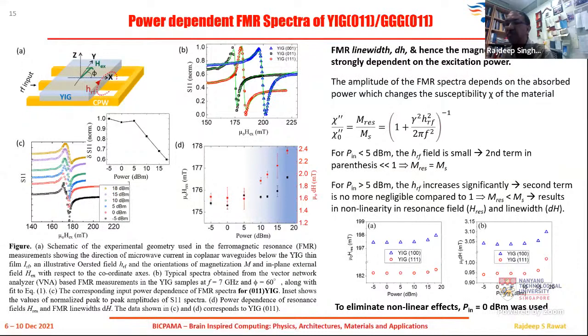But first of all, we wanted to make sure this two-magnon scattering does not come from the use of very high power. So we wanted to see the region where the response can be nonlinear by itself just because of the power, and we did not want to work in that region. So the input power was changed, because even a high input power can cause line width broadening as well as magnon excitation. The power was changed from -5 dBm all the way to about 18 dBm, and at these various powers you measure the resonance field as well as the ΔH values. As you can see, at the lower powers they were more or less constant and linear, but after that they start to go into the nonlinear regime.